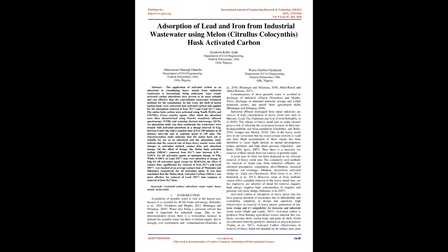removal of iron, Fe2+, and lead, Pb2+, ions. The melon husk carbon was activated using NaOH, H2SO4 and CO(NH2)2, urea, reactive agents. After which the adsorbent was characterized using Fourier transform infrared spectroscopy, FTIR, and scanning electron microscopy, SEM. An adsorption study was then conducted.